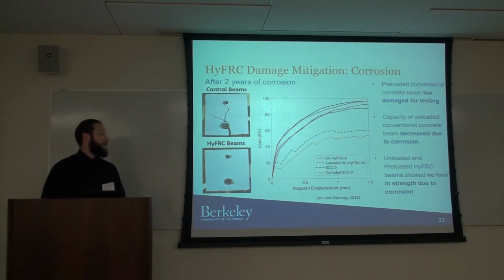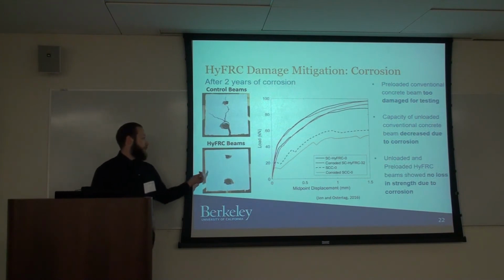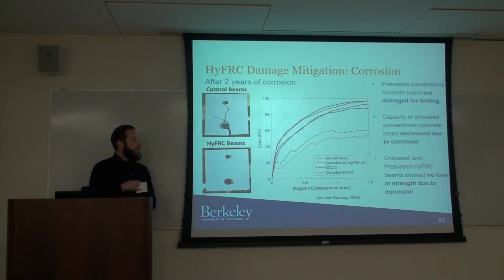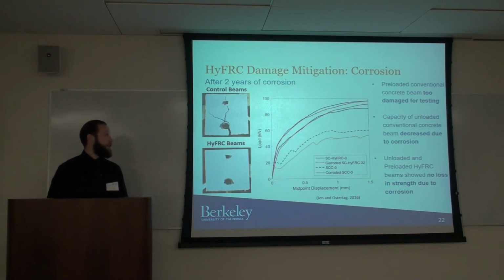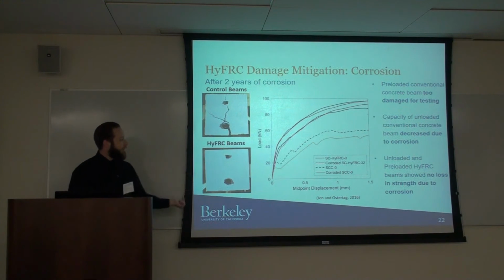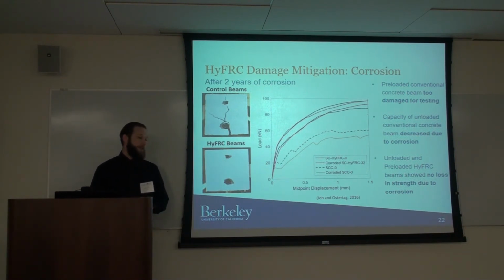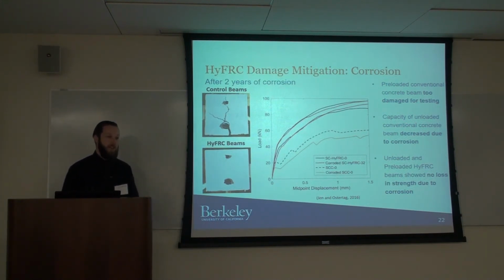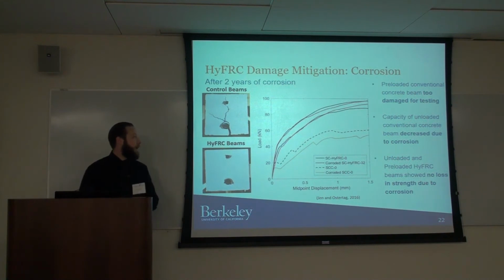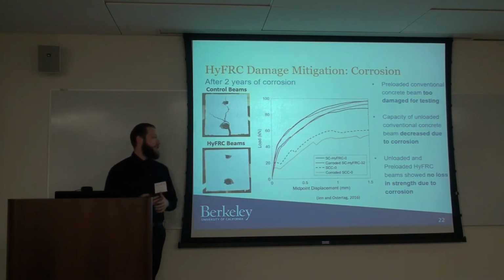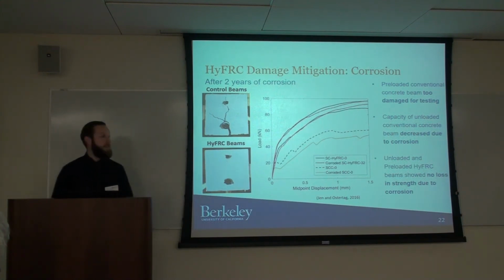And if we look at the flexural behavior of these elements before and after corrosion, the top specimens are our hybrid fiber reinforced concrete specimens, with the black line showing the behavior prior to corrosion. So these were sacrificial specimens, obviously. And when compared with elements after 2 years of corrosion damage, they achieved very similar behavior. Whereas with the conventional concrete specimens, the preloaded specimens, which you see here, were too damaged to test after the 2-year period, so they essentially had no residual stiffness left. Meanwhile, the control specimens, which were unpreloaded, could be tested after the 2 years, but even in those you see a significant decrease in strength.